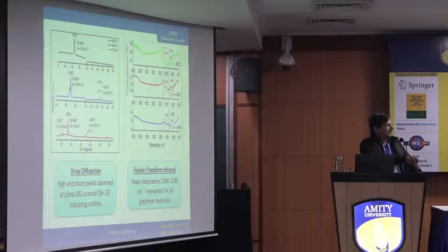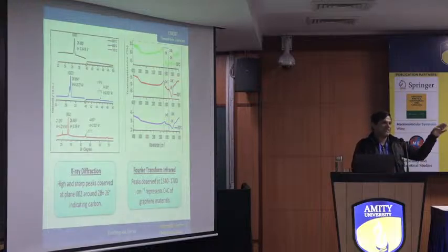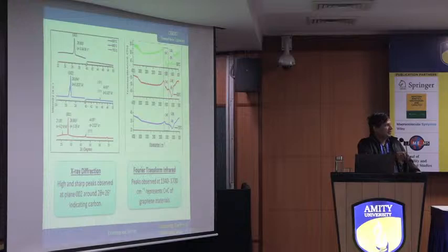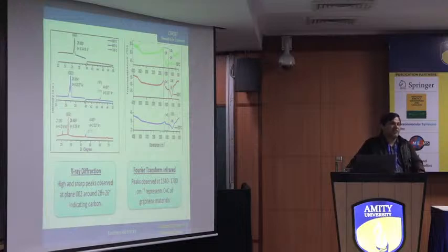You can see this is the nanoparticle synthesized at 3 different temperatures. In all 3, you can see a perfect crystalline peak, and this peak represents carbon. You can see 26.8 degrees, which represents the carbon. So now it says that this nanoparticle is carbon in nature. As you increase the temperature, you have multiple peaks, and these multiple peaks suggest that you are going towards a graphitic structure. Maybe if I go to 2000 degrees, I might end up with graphitic structures.